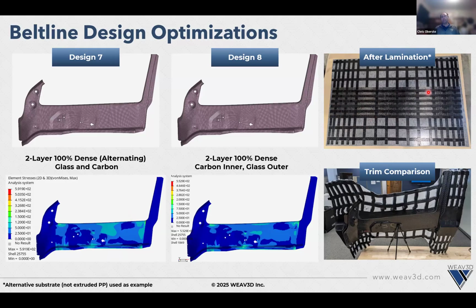And you can see that we've actually tailored this lattice so that we have a lot of material in the middle. You can see that in this bottom image where I've laid one of the trimmed parts over an untrimmed piece. You can see where the high density region aligns with that middle region of the trimmed part right here. And then towards the edges, where we're either going to trim material off or where it's only going to be the A or B pillar, we've decreased the density in order to get our cost optimization to where we want it to be.